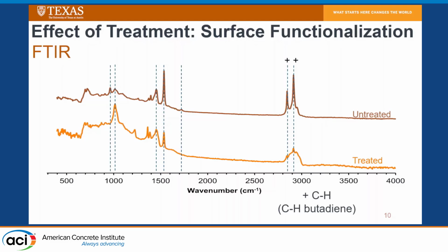So over here, these wavelengths correspond to our carbon-hydrogen bonds, particularly when we look at rubber. What we see is that this corresponds to this hydrocarbon butadiene that is essentially this waxy coating that is on the tire rubbers, and that is something that is going to increase the hydrophobic nature of the rubber.